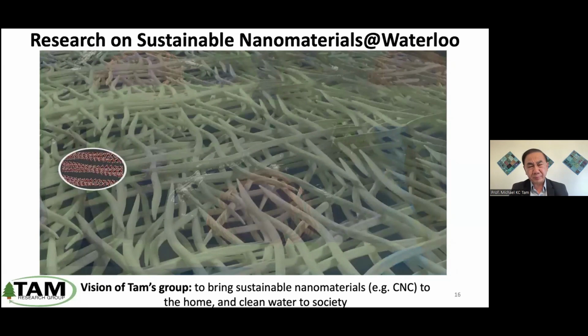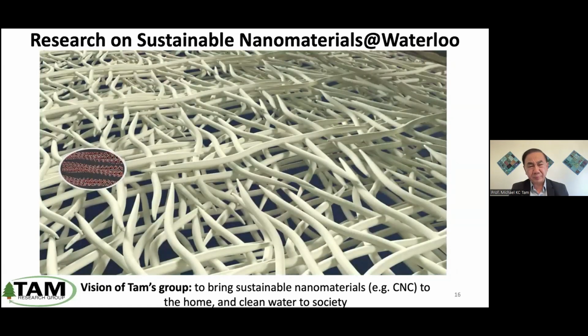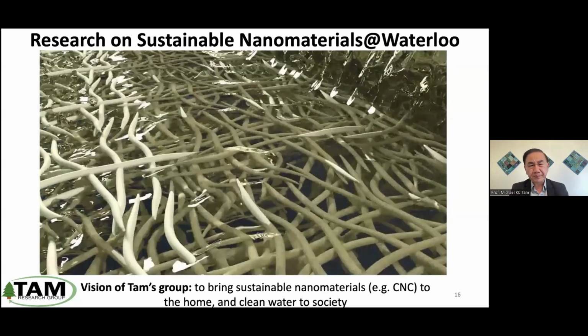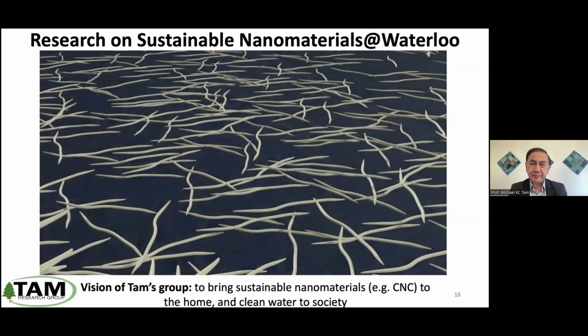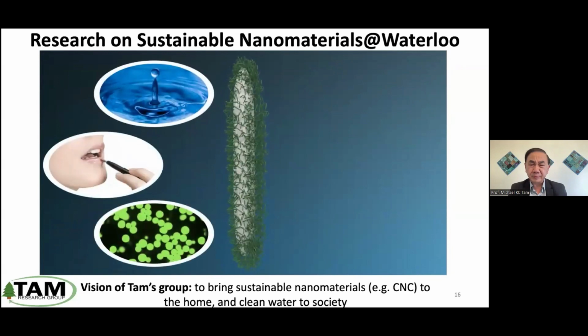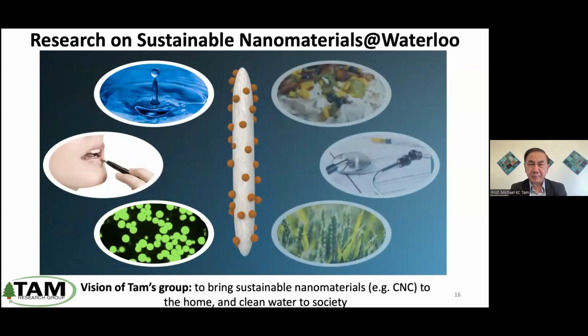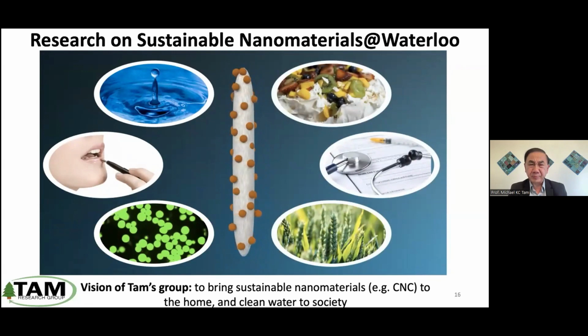The scale-up process begins when highly organized cellulose fibers derived from wood undergo acid hydrolysis to yield the crystalline domains of the fiber, known as cellulose nanocrystals. The crystalline rods have remarkable surface area and mechanical strength, providing a unique avenue for the prospect of scalable and sustainable applications. Some of these applications include grafting of polymer brushes for wastewater treatment, cosmetic and personal care, preparing emulsions, and oil and gas. Surface modifications with functionalized coatings and metal oxide deposition can be used in food, healthcare, and agricultural applications.